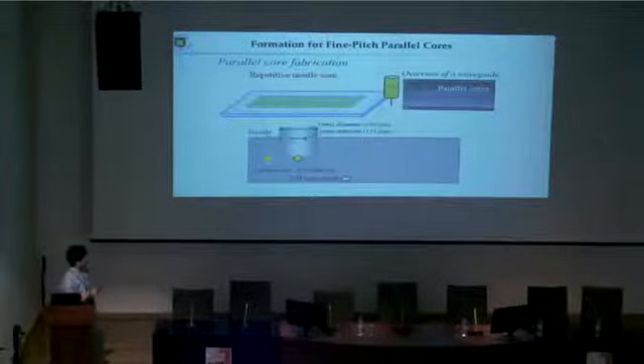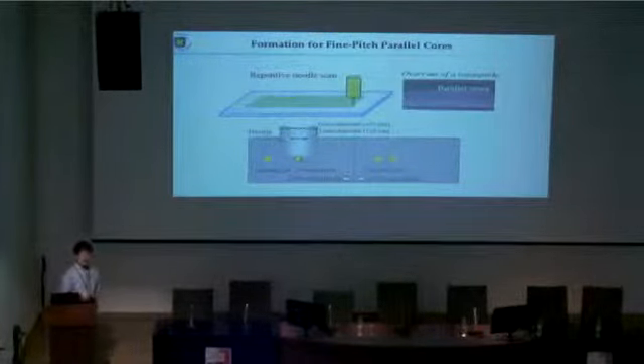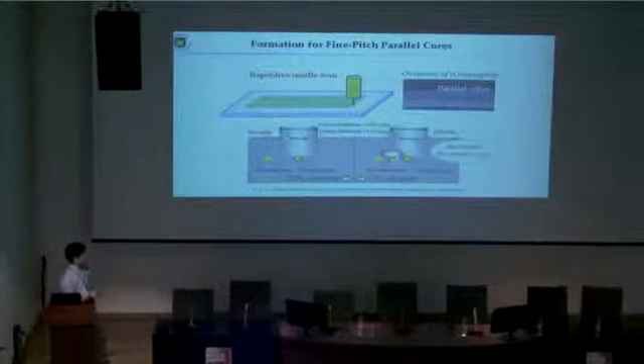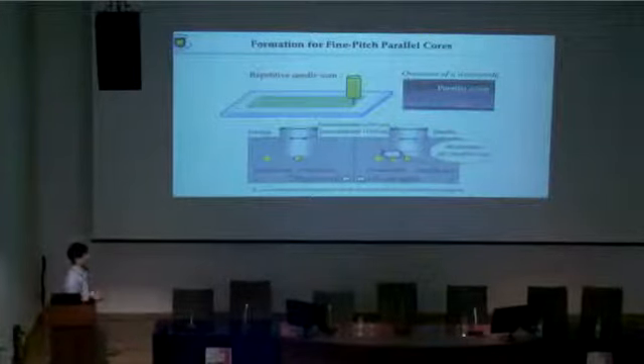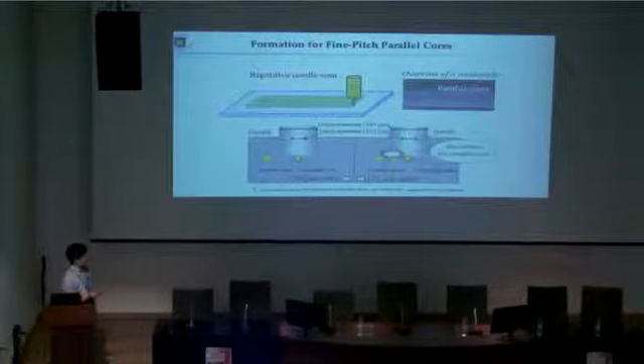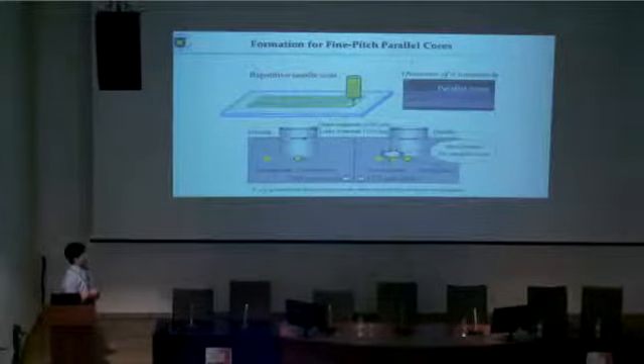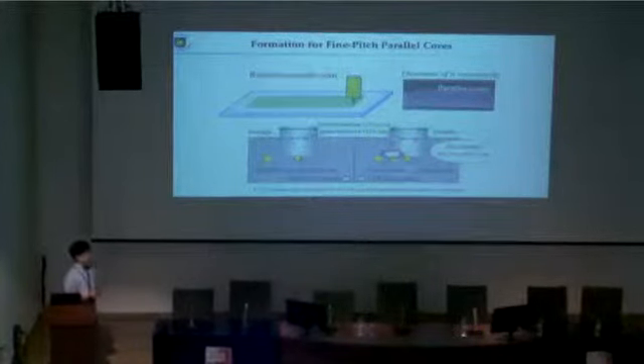Therefore, the formed core previously dispensed is a little bit far from the edge of the needle. Therefore, even if we apply multiple scans, the core alignment is not affected by this needle. On the other hand, in the case of half pitch, 125, no more wide tolerance is obtained, but the edge of the formed core is now within the outer diameter of the needle. Therefore, in the process of the multiple scan, the core alignment may deteriorate.